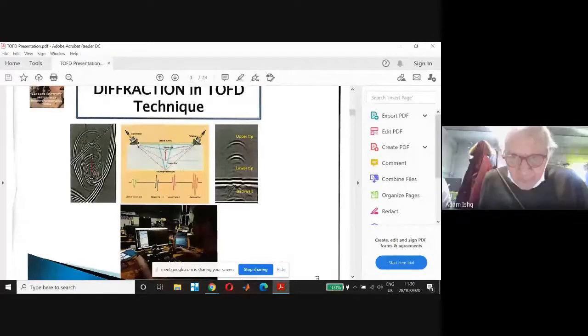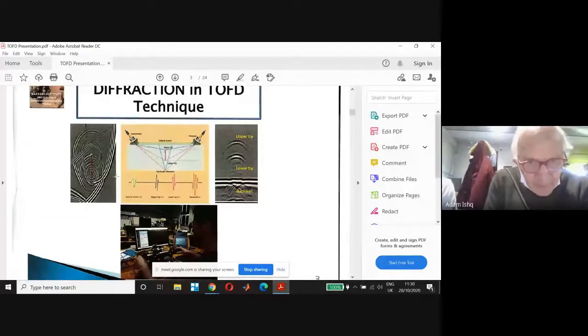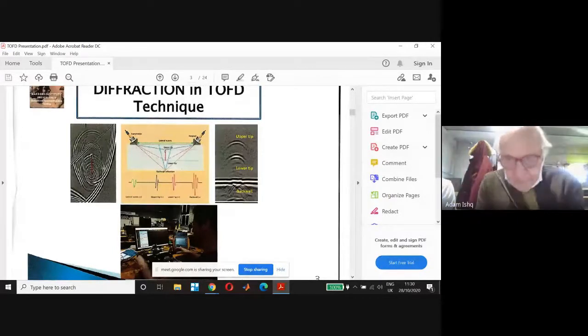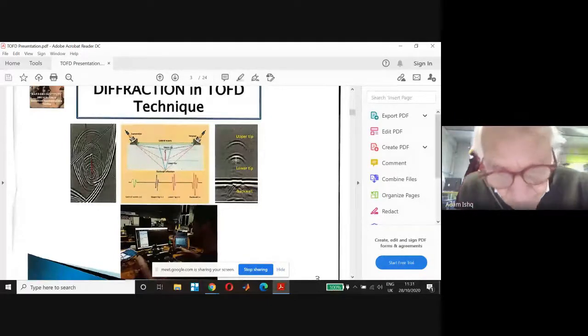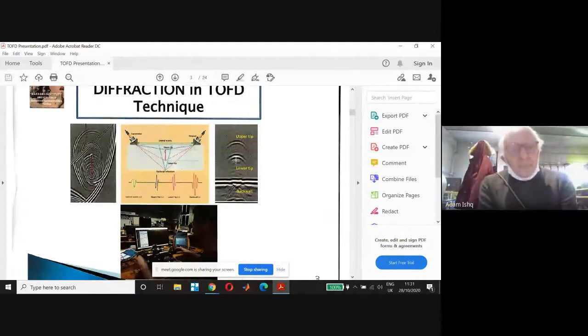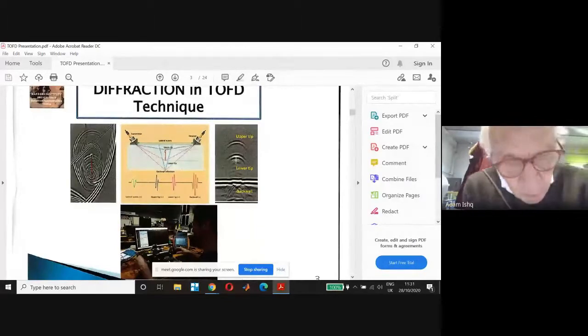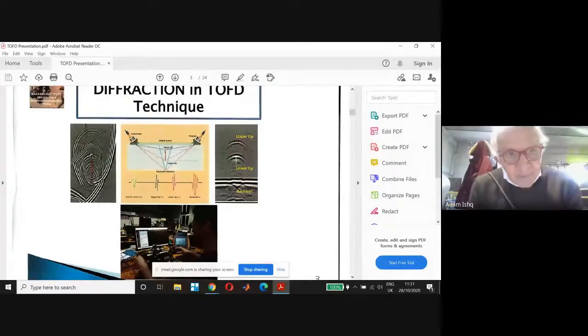Okay. So, look, this is the basic. At the left you see what happens inside the material, and at the right side you see the main wave. When the main wave comes over the crack, it generates two spherical waves. The software makes its work and projects on the monitor two signals, of the upper tip and the lower tip. This distance gives you, with an accuracy of less than 1 millimeter, the height of your crack. Also, if the crack is 3 millimeters high, this shows the very high sensitivity of time of flight.